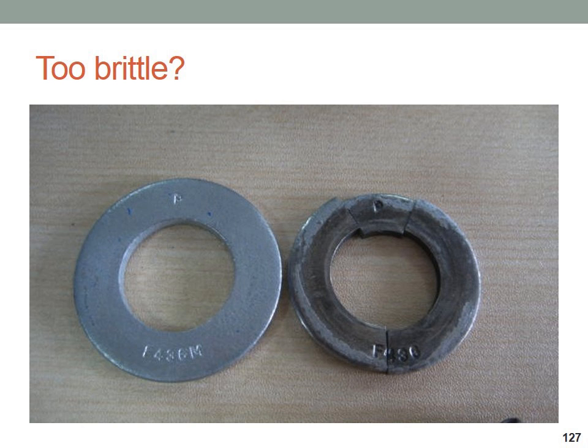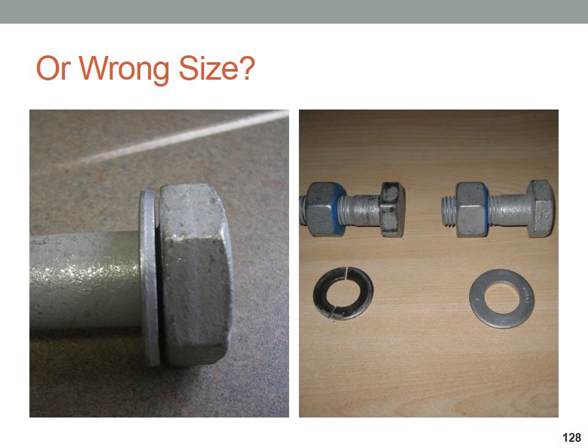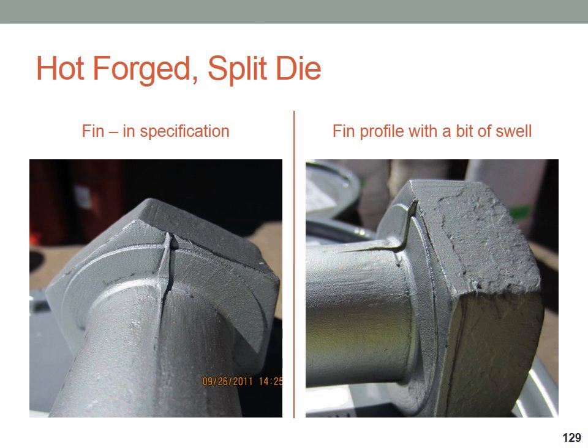We had a customer last year come to us and say that some washers they were using were too brittle and they were cracking on installation, and they sent us samples and we couldn't figure it out. I'd honestly never had a washer crack in my experience. Through some additional investigation, we found out that they were putting inch series washers on metric fasteners simply because they fit. They got them mixed up at the job site, and the radius underneath the bolt head was putting so much outward pressure on the washer that they split. And once they realized they had mixed up some components, that got fixed quite quickly.